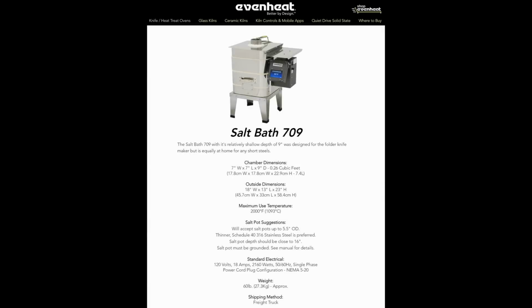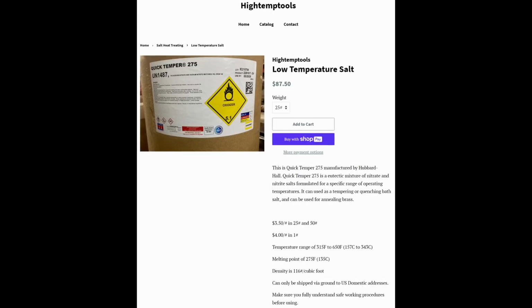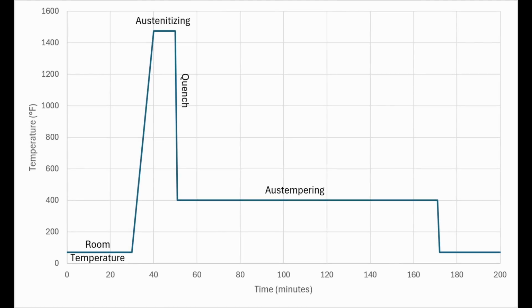Now, like in my last video about austenitizing in salt pots, I used my same even heat salt pot. This is the 709, but in this case, I used a second pot that I have, which is filled with low temperature salts that I bought from High Temp Tools. These low temperature salts have a melting point of about 275 Fahrenheit, and the working range is supposed to be 315 to 650 Fahrenheit. And that allows us to quench and hold at these intermediate temperatures.